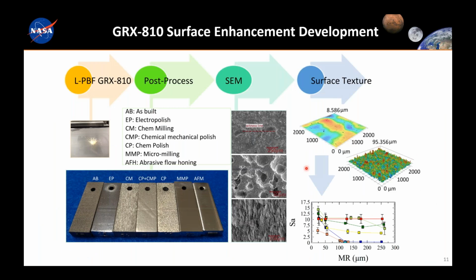We have developed some other post-processing enhancements as well, particularly surface enhancements. And I'm not going to go into a lot of detail on this. We have some papers that will be coming out very soon on this, but we've applied different processes that you would use to polish the surface, such as electropolishing, chemical milling, chemical mechanical polishing, micromilling, and abrasive flow machining. And again, with each of these techniques, we see very similar results to what you'd expect with the more traditional nickel-based superalloys. So the yttria oxide in there is not affecting any of the machinability or any of the post-processing that we would typically use on these additively manufactured materials.